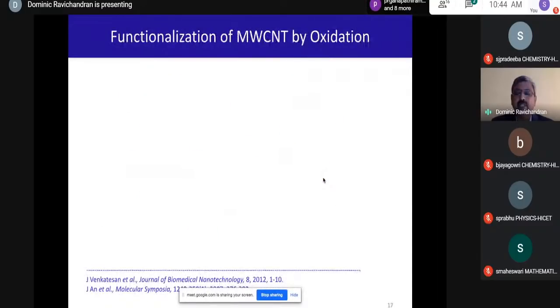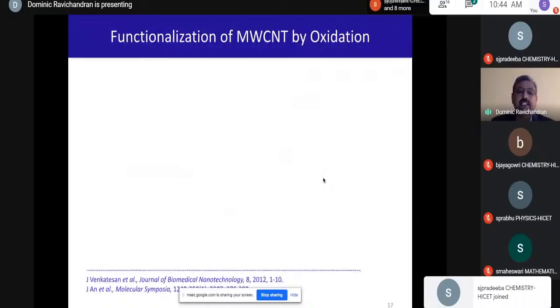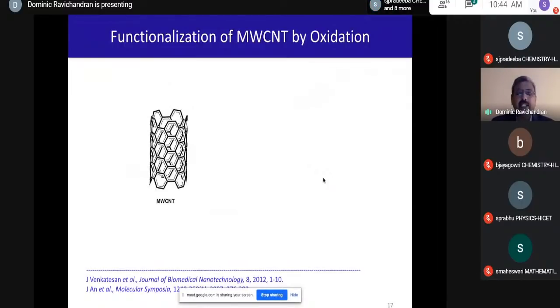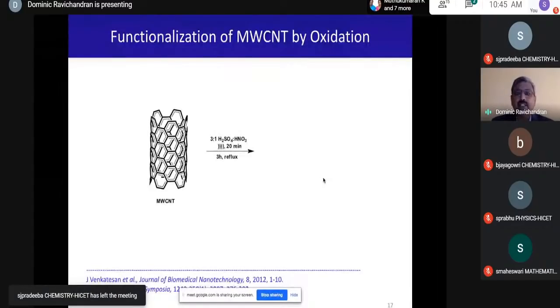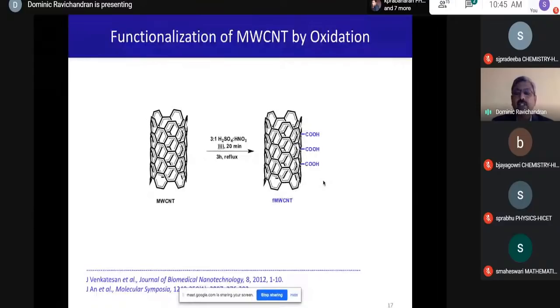When we come to the functionalization of multi-walled carbon nanotubes, it can be done by oxidation. In multi-walled carbon nanotubes, the multi-layered graphenes are rolled, so you have too many layers of graphene. It can be functionalized using a mixture of acids like sulfuric acid and nitric acid in a ratio of 3:1, sonicated for 20 minutes, after which it is refluxed for 3 hours to get the functionalized multi-walled carbon nanotubes.